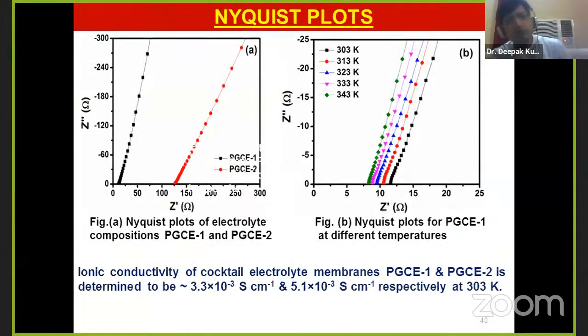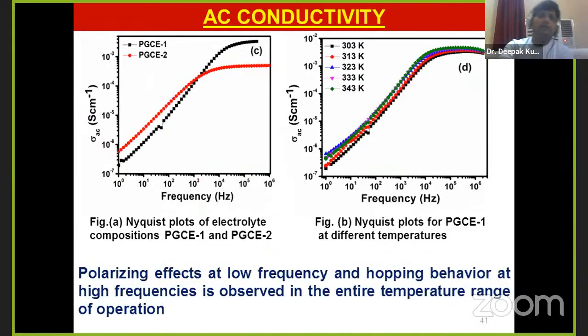The Cole-Cole plot shows that the bulk resistance of this electrolyte system is very low, which indicates the material is going to be a good ionic conductor. And in fact, we have observed a conductivity of 10⁻³ Siemens per centimeter, which is considered to be good for any electrochemical system. We have also plotted the AC conductivity features, and from that we can see at the low frequency the polarizing effects are prominent.